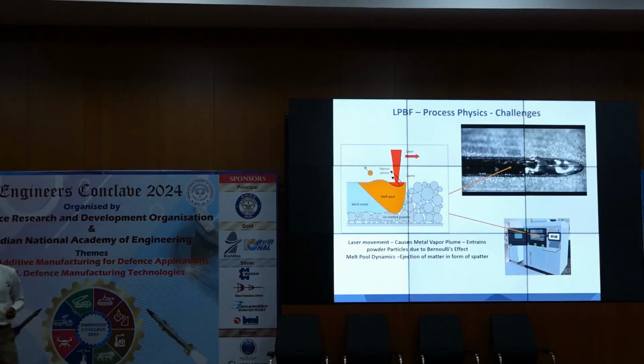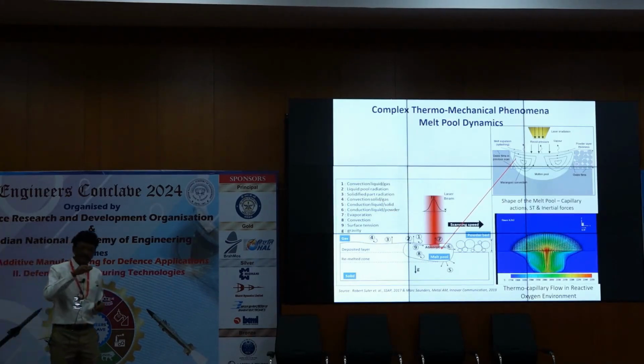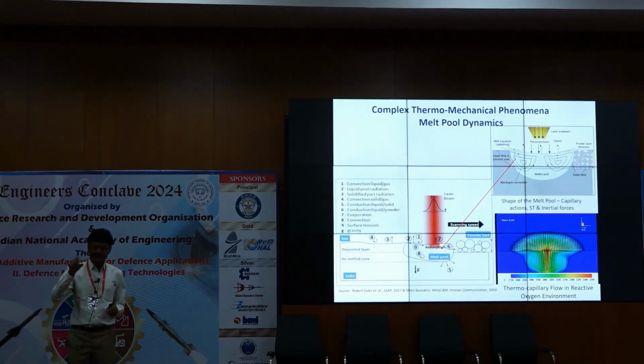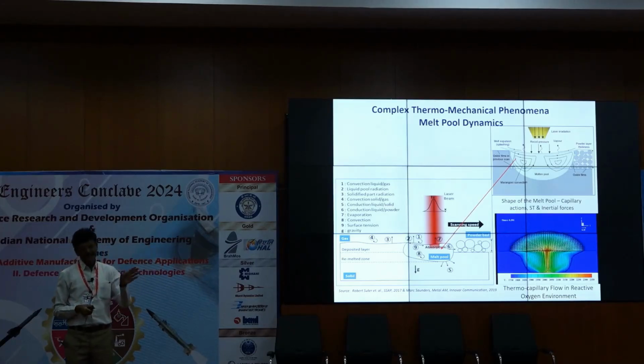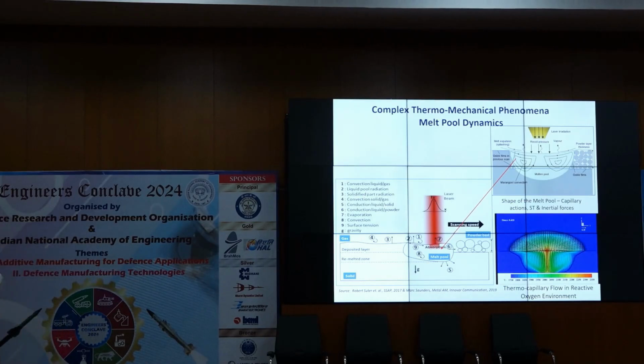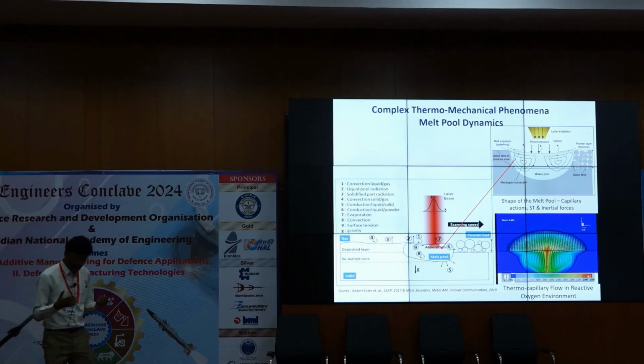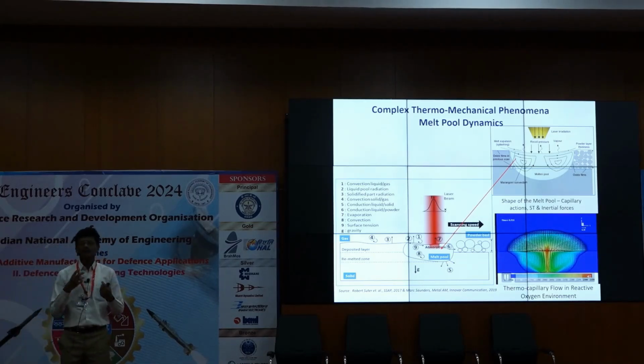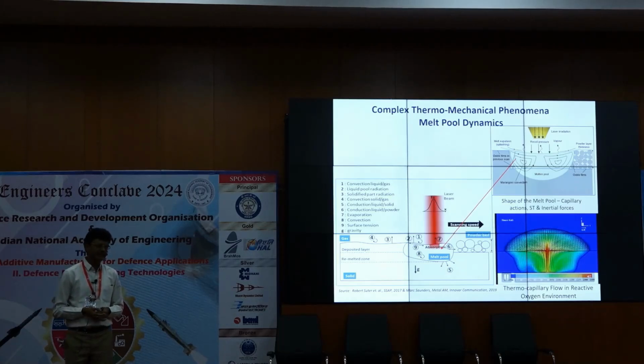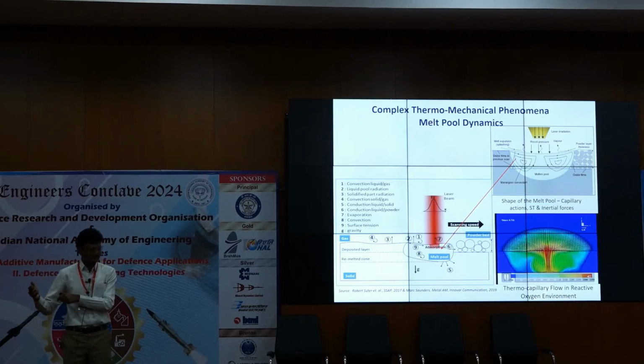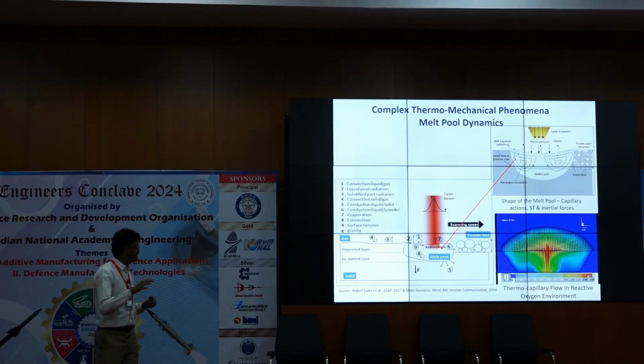Though the energy across the width of the beam varies marginally, that leads to differences in the surface tension, and these surface tension related differences cause turbulence in the melt pool, and the melt pool size is not only influenced by the capillary forces, it is influenced by the surface tension gradients and also inertia forces. Interestingly, the gravity doesn't impact it. That's the reason why you might have seen many case studies where people are talking about additive manufacturing in the microgravity. So contrary to what we think, the gravity doesn't impact.